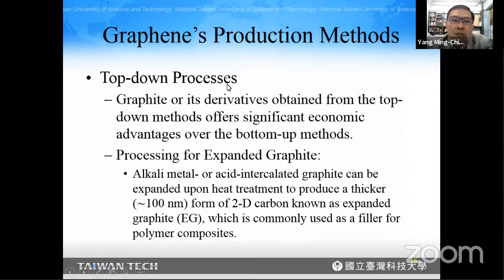Now, the other type is the top-down process. In this process, graphite or its derivatives obtained from the top-down method offer a significant economic advantage over the bottom-up method. Basically, they are based on the exfoliation of expanded graphite. And this expanded graphite was obtained by alkali metal or acid intercalation in graphite, which can be expanded upon heat treatment to produce a thicker form of two-dimensional carbon known as expanded graphite, which is commonly used as a filler for polymer composites.